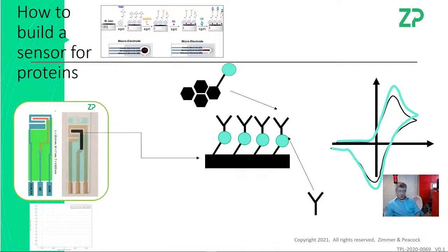So this person wants to make an HIV sensor. Therefore, they need to recognize what's the macromolecule that's going to give me specific binding to HIV, let's say. So they have to identify that. At which point, they can take the carbon electrode and add a reagent called pyrene NHS. That will give them a surface of NHS moiety, to which they can then bind their chosen antibody, and then they will block the surface in a second step using BSA, bovine serum albumin, or they can use things like chitosan.